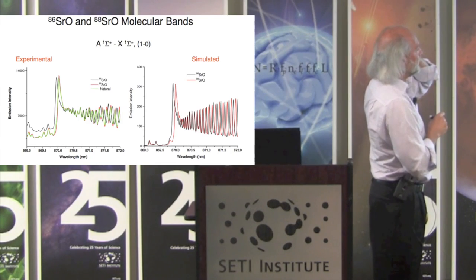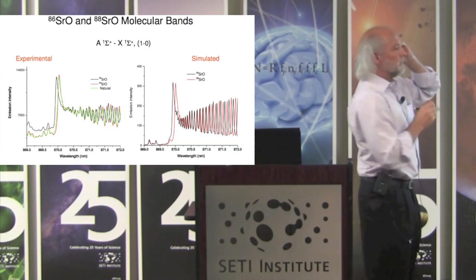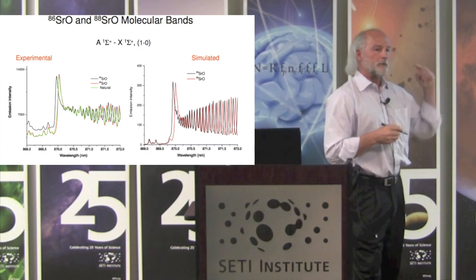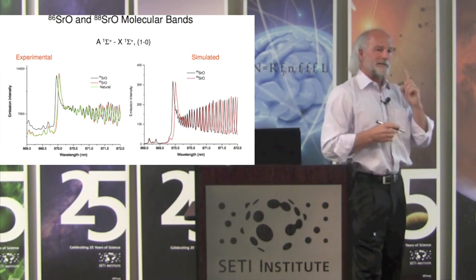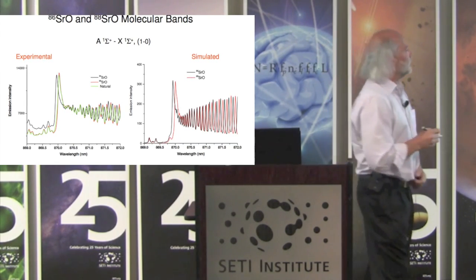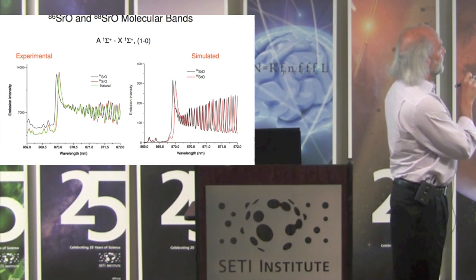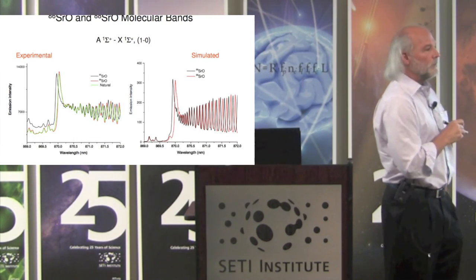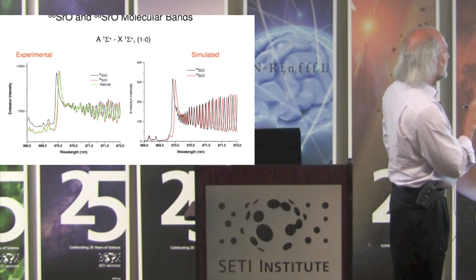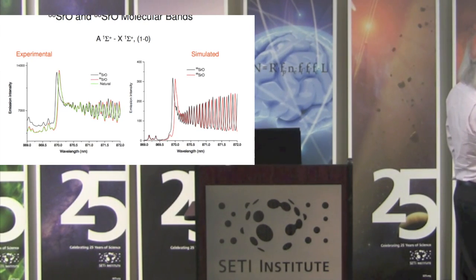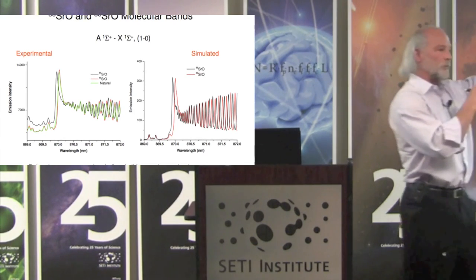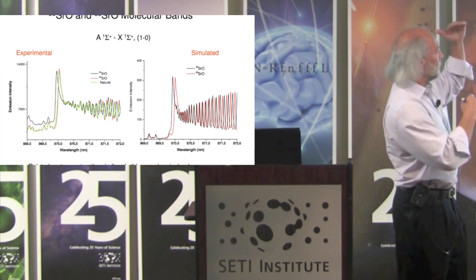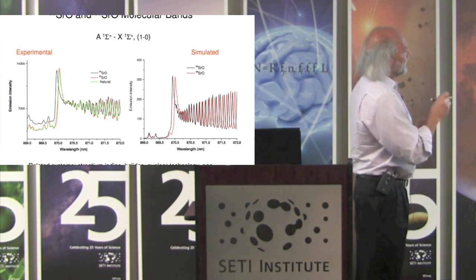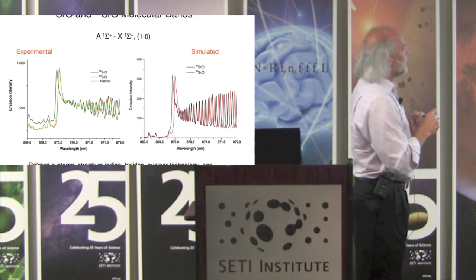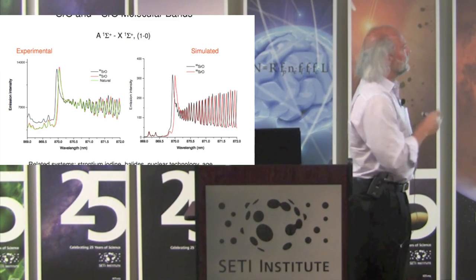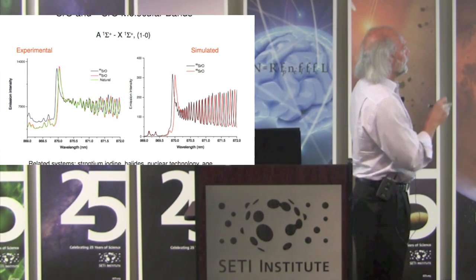Strontium, 86, 88. No way can you do a strontium isotope looking at an atomic transition. The atomic transition is less than one picometer shift. So for the 86, 88 strontium molecular, depending on what band we're looking at, this is the A1 to X1 band. Again, that has to do with what excited state versus what ground state, what vibrational levels. Depending on what wavelength region, we can see anywhere from about 100 and up in terms of the isotope splitting.